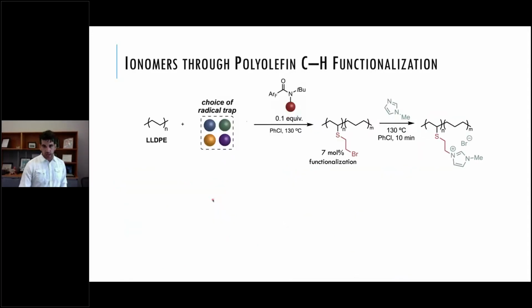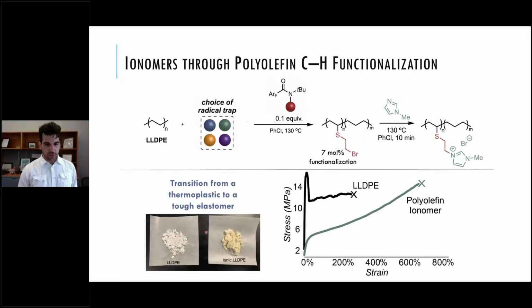So we showed we can do that by first using our reaction to add this primary bromide and then making an ionic species here, this imidazolium ionomer. And again, you can see the material just visually changes a bit. When you press it, it has increased clarity. But the real key here is the linear low density polyethylene that we made this material from.